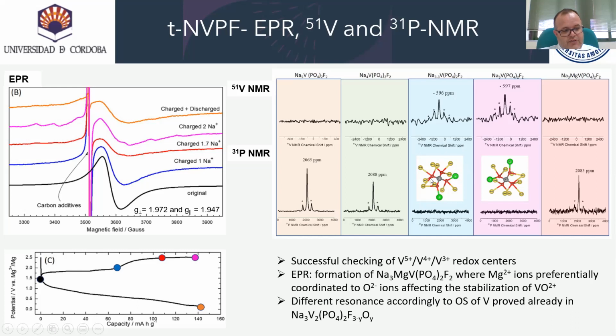After a total charge, the sodium extraction provokes the disappearance of the 31 phosphorus signal. Then, after a complete discharge, we observe that the signal is recovered. It seems that here, the oxidation of vanadium to vanadium 4 and vanadium 5 creates a diminishing effect in the resonance signal of 31 phosphorus.